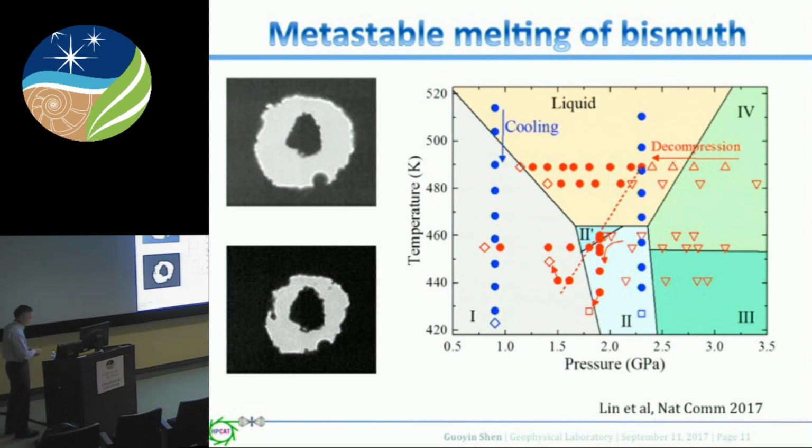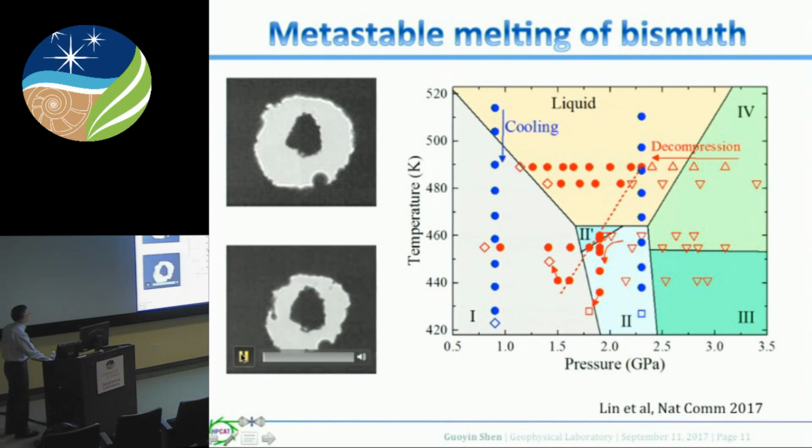It's not the morphology of liquid. But as we keep going and then decompress, the edge becomes round and displays a morphology that seems to be related to liquid. So we are convinced that the non-crystalline pattern we observed from X-ray diffraction is really the liquid.